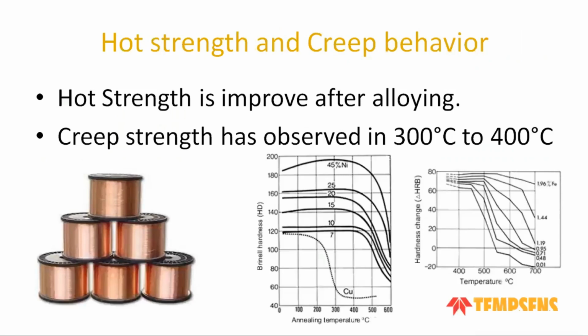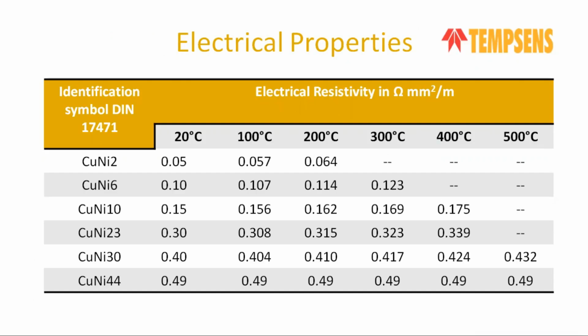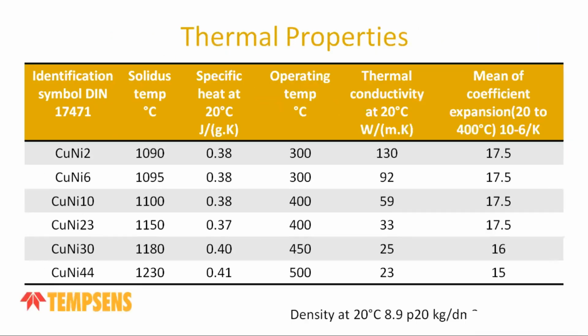Let's begin with the hot strength and creep behavior. After alloying, hot strength has been improving, and creep strength is observed between 300 to 400 degrees Celsius. The operating temperature is 300 to 500 degrees, which is much more efficient. With this temperature alloying, this is the range in which creep plays a very important role. That is the main important factor.